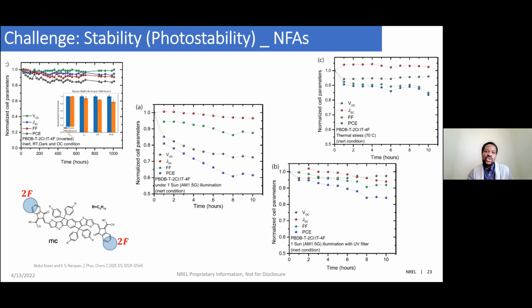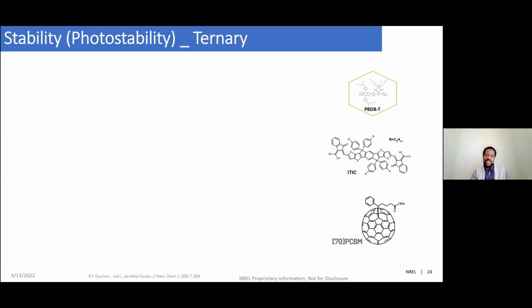So what can we do to really help the technology? So the idea that came was, okay, if ITIC-based devices perform that well in terms of efficiency and they are degrading, why not try a ternary blend? So what we did is to keep this ratio, the ratio of the polymer and the ITIC, the ratio of the polymer constant, and then we increase the amount of [70]PCBM in the blend with what we are losing from the ITIC. And you can see that this is a trial and error